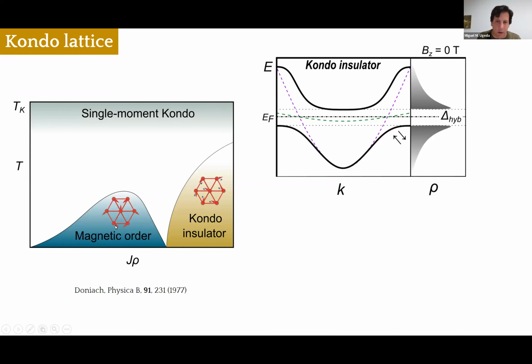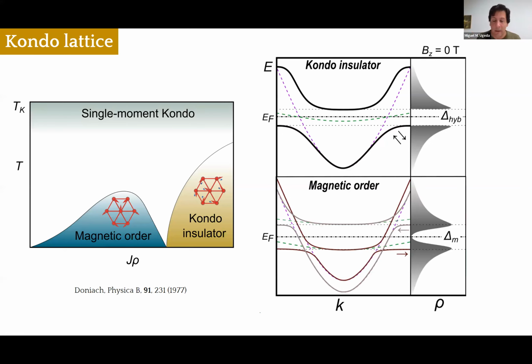In the magnetic order ground state, the situation is relatively similar. There is a hybridization of the bands, but in this case, the magnetic order leads to the formation of spin polarized bands in the conduction band and in the valence band. So basically it forms a magnetic gap as well, as you can see here. So in the absence of magnetic field, the situation is really similar, and it's a bit ambiguous to distinguish between these two ground states, right? However, there is a key difference between these two band structures, which is that in the Kondo insulator regime, we have spin-degenerate band structures, whereas in the magnetic order state, we have spin-split bands.